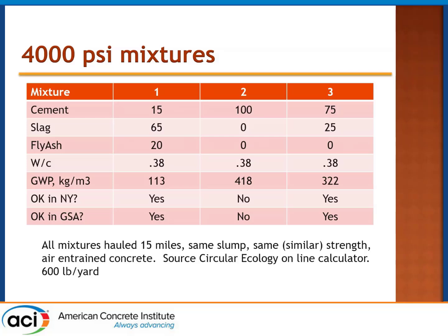The global warming potential is calculated in kilograms per cubic meter below, and you can see that I can make it really low. 113, that's super low. That meets everybody's requirements. So using straight cement, which many floor finishes require, does not meet those requirements. And further, the 25% slag does, but I picked 25% on purpose.